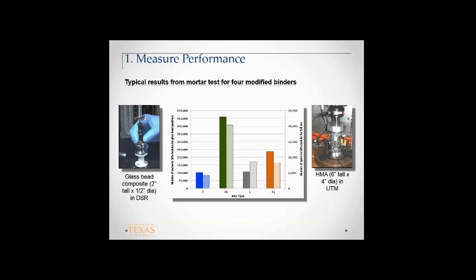So they are not the same grade. They are very similar continuous grade, that close to each other. All these binders are from the same crude stock, same refinery, same source, but they've just been modified using different polymers in different proportions, and as a result of that, you get very different performance characteristics. So if you go by the binder spec, all of these binders should be exactly the same, but they're definitely not. So you'd see that in this case, these binders have a very different result. What you see on this axis here is the fatigue life.